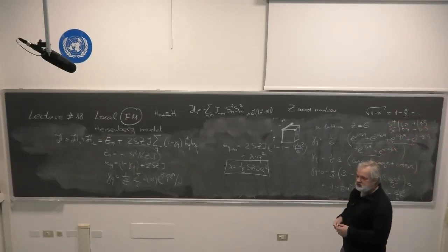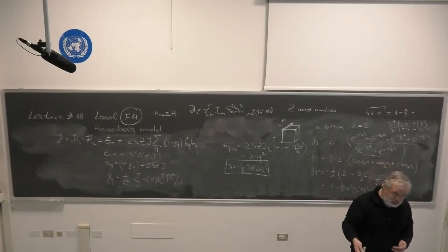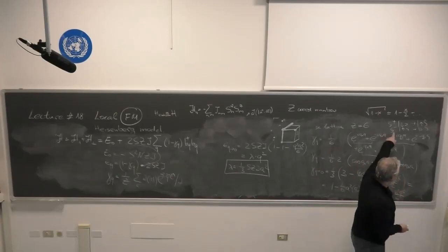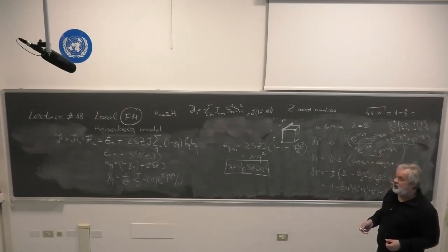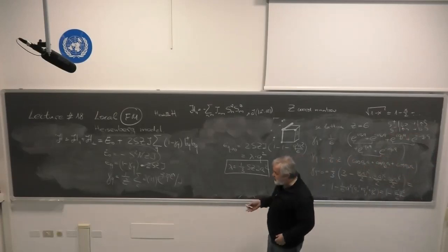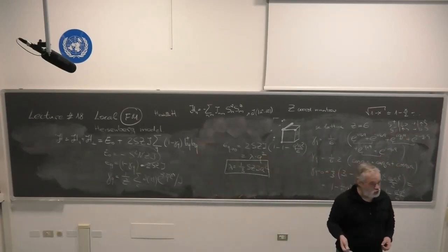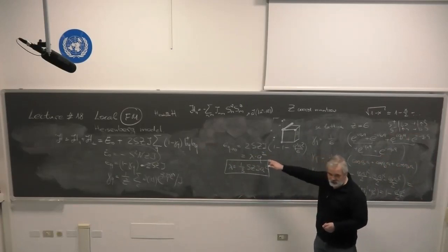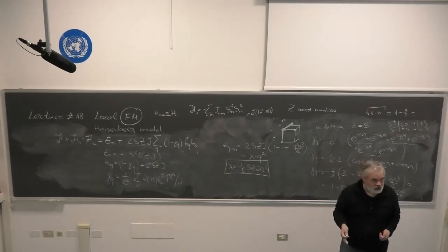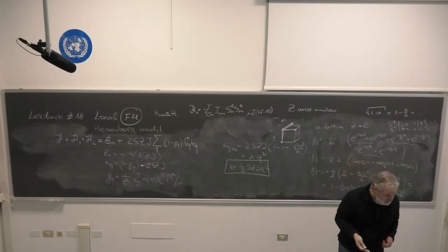So this bosonic operator, corresponding to increasing the projection by 1 or spin flip, is called a magnon. So we found the excitations in the Heisenberg model at very low temperature. We showed that these excitations are bosons. We call these bosons magnons. And what we have found, the dispersion of these magnons at small q in the long wave limit, is proportional to q squared.